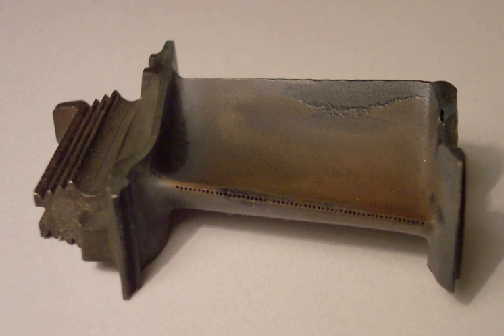The properties of these Ni-based superalloys can be tailored to a certain extent through the addition of many other elements, both common and exotic, including not only metals, but also metalloids and nonmetals. Chromium, iron, cobalt, molybdenum, tungsten, tantalum, aluminium, titanium, zirconium, niobium, rhenium, yttrium, vanadium, carbon, boron or hafnium are some examples of the alloying additions used. Each of these additions has been chosen to serve a particular purpose in optimizing the properties for high-temperature application.